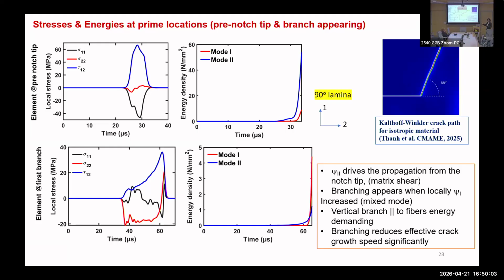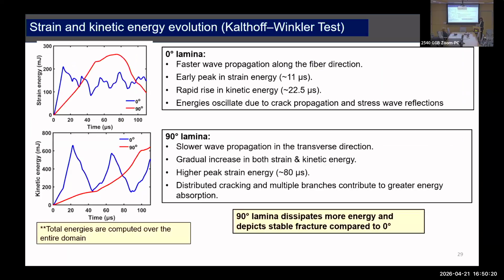Just to give you a reference, in the literature there have been quite a lot of Kalthoff-Winkler experiments and simulations. In an isotropic material, with the same boundary conditions and same geometry, the crack propagates in pure shear driven mode like this. Just to give you some inference of what happens in the regular isotropic geometry.